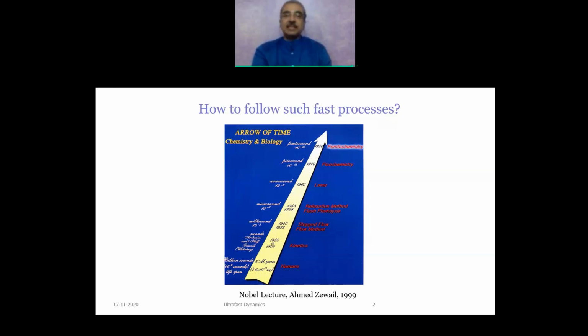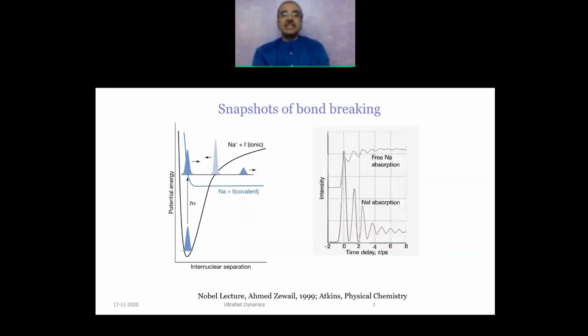Pratibha, next slide, please. And using these femtosecond lasers, what Zewail's group had done was something beautiful. They took what they called photographs of a bond breaking. Without going into the detail of the instrumentation, what this curve here shows is how the population of sodium iodide decays. And the reaction that's happening is that you start with sodium iodide and then it breaks up to give you free sodium and free iodine. So the population of free sodium increases with time, population of sodium iodide decreases with time.